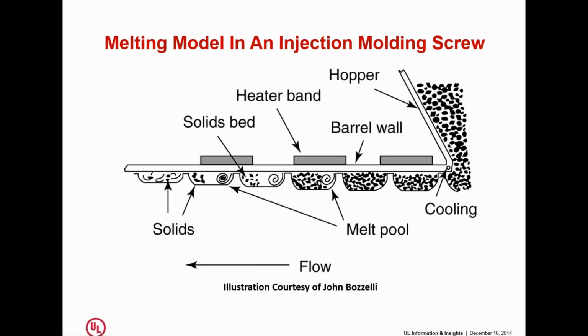Getting these melted when we no longer have direct access to them, the direct ability to generate the compression and the mechanical work that's designed to produce the heat needed to melt the material, produces a whole range of symptoms, like the color swirls I mentioned, like unmelted pellets, which many of us have seen, especially when we're running semi-crystalline materials like nylons and acetals and polyethylenes. Excessive screw wear because we have pellets getting in between the barrel and the flights, and when they're really hard and rolling over the flights.